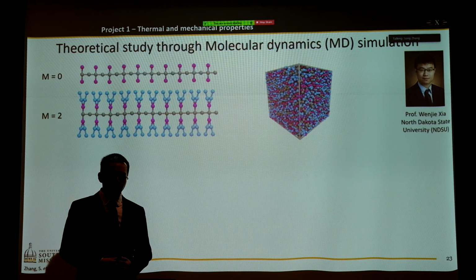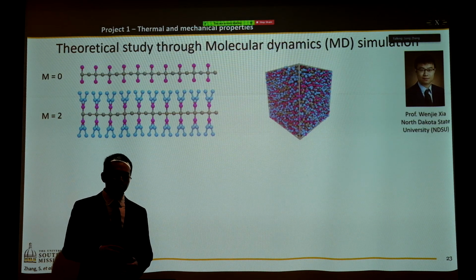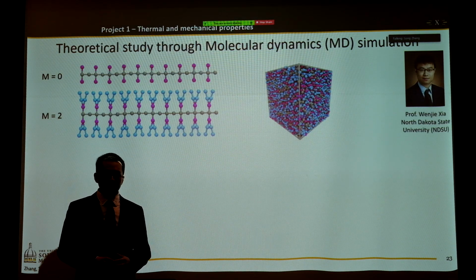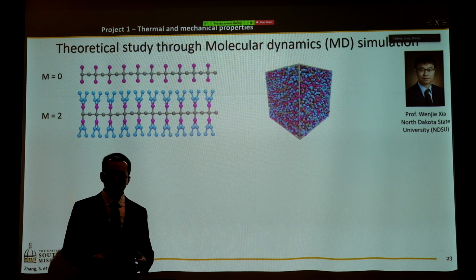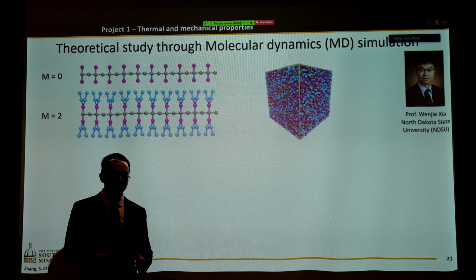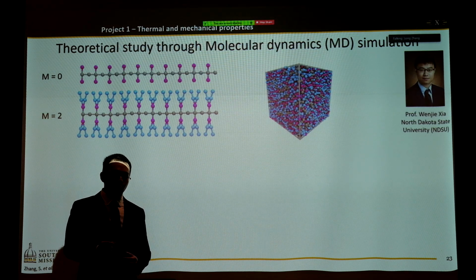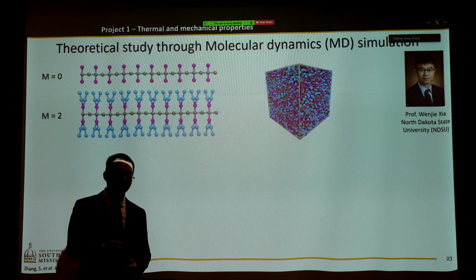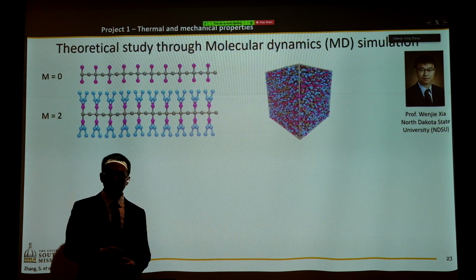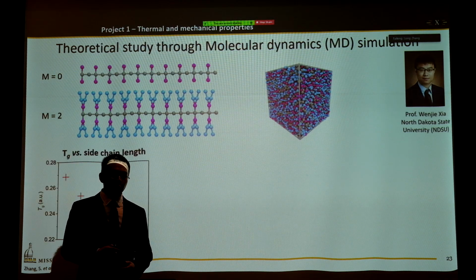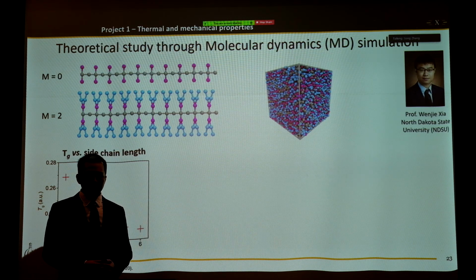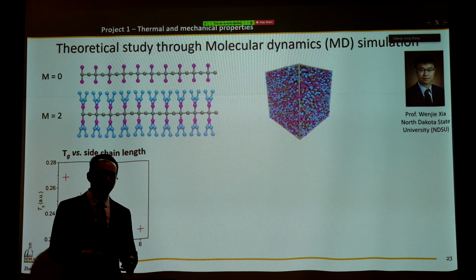So we collaborated with our collaborator, Dr. Xia from NDSU. He helped us build this coarse-grained model, where the backbone is represented by the gray beads, the red beads represent the branching unit, and the blue beads, or the M value, represent the side chain length. And we find that with increasing side chain length, the Tg drops in a curvy way.